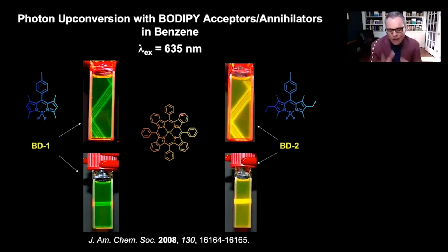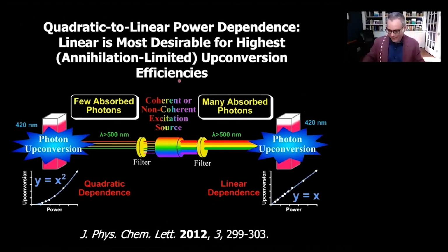But again, they all follow the same design principle, is the singlet and triplet levels of the sensitizer are really sandwiched in between those of the acceptor annihilator. And if you just follow that simple rule, you can find enormous numbers of dye molecules that have low energy triplet states that are able to annihilate, even laser dyes. So I would highly recommend, feel free to explore.